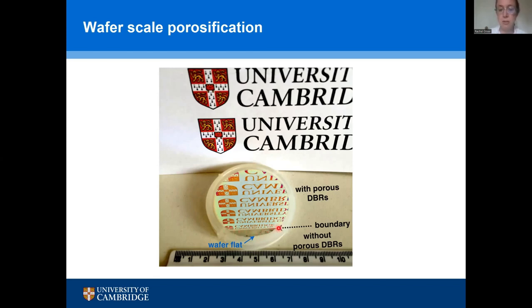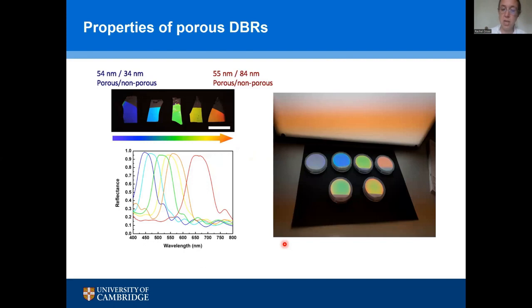Over the vast majority of this wafer surface, it's completely unpatterned. It was just etched as grown as a full wafer. And we can change the layer thicknesses in our mirrors to change which wavelength they preferentially reflect. So we might have thinner layers to reflect blue light, or thicker layers to reflect green or yellow or even red light. And we can achieve reflectivities that are quite high, in excess of 90% across the board. You can see that here for full wafers, as well as these little test samples at the top.